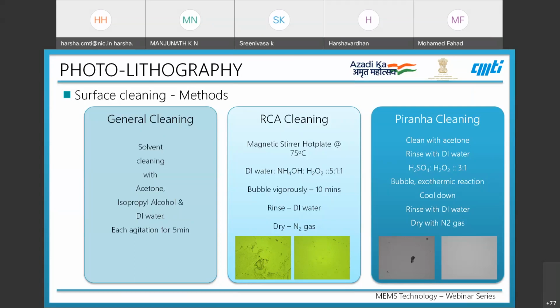It could be metal impurities or organic impurities. For organic impurities, we use NH4OH, and for metal impurities, we use HCl. After the exothermic reaction, we rinse with DI water and dry with gas. The two images show before and after of a sample: the left-hand side shows the sample before RCA cleaning, and the right-hand side shows the cleaning done after RCA.